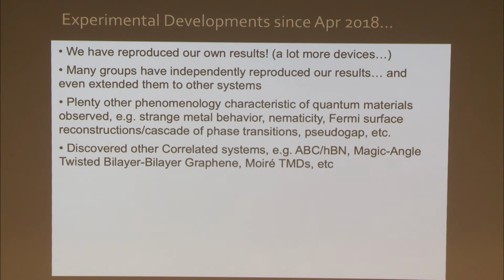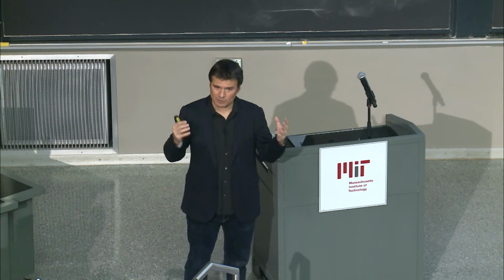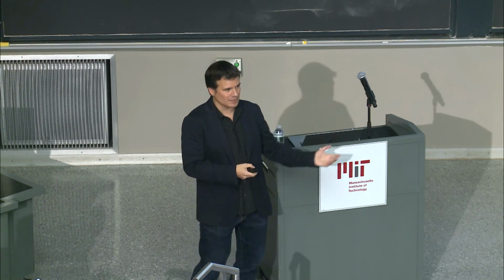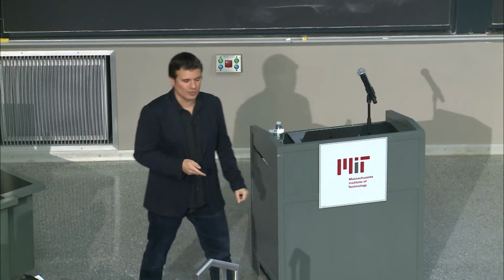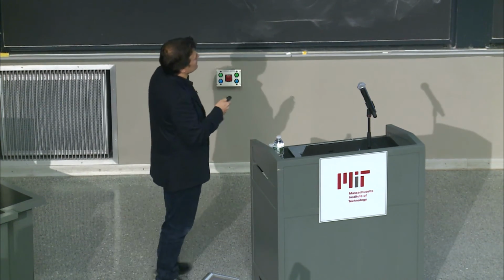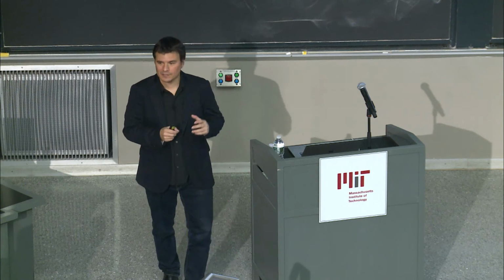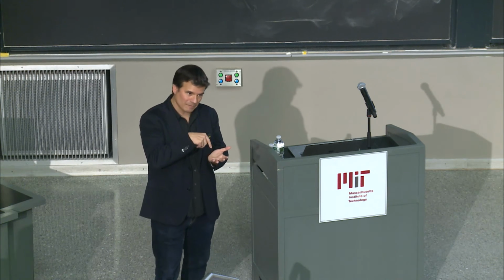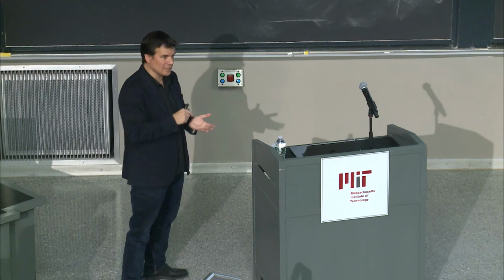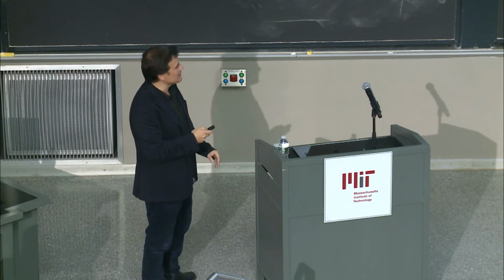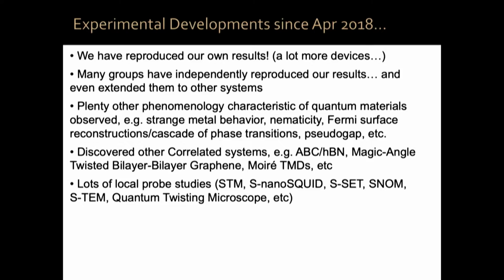Now, initially, most of the information about the system was coming from quantum electronic transport measurements, resistivity versus various parameters, field effect transistor geometries, etc. But what has happened is that now, there are lots of local probe studies. People that have tips that can look microscopically at what's going on in this Moiré system have been investigating the systems. In particular, people do scanning tunneling microscopy, scanning nanosquid, scanning single electron transistors, scanning near field optical microscopy, scanning transmission electron microscopy. There is even something called the quantum twisting microscope.